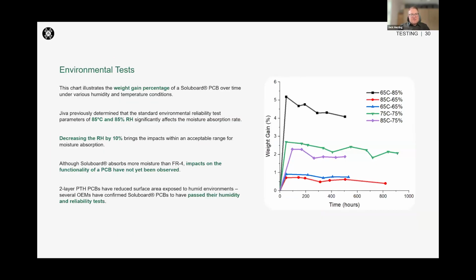Environmentally, one question that we're always asked, and it's a valid question, is about our resistance to humidity and our reliability. So we do tend to have a slightly higher moisture absorption, so a higher weight gain percentage than the likes of FR4. And the typical environmental and reliability test is 85 degrees Celsius, 85% relative humidity for 1,000 hours.